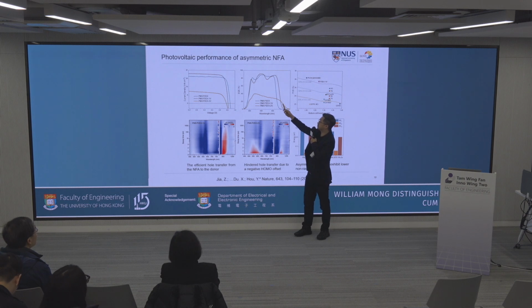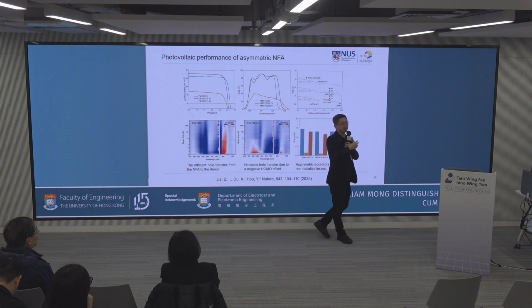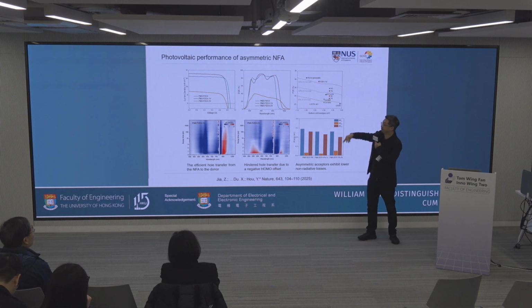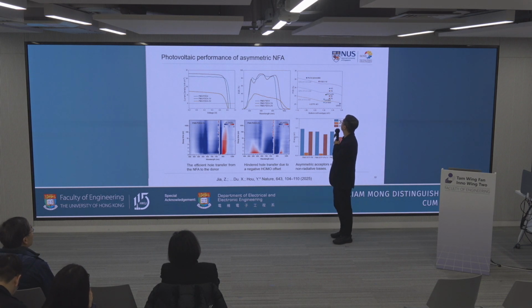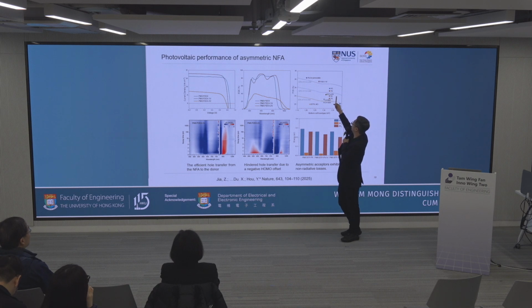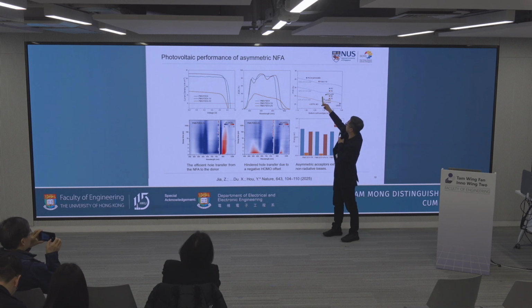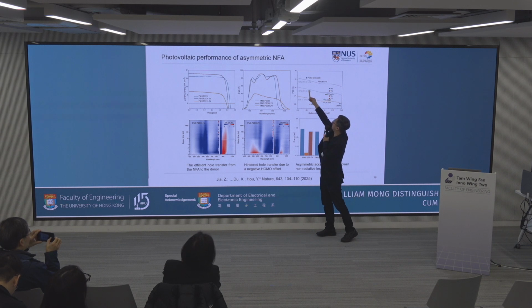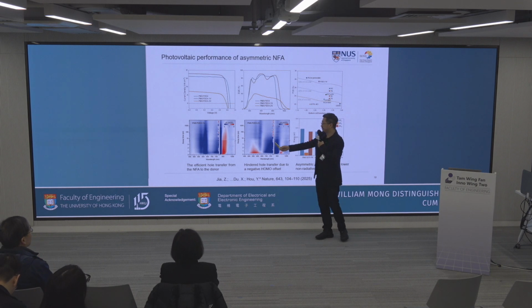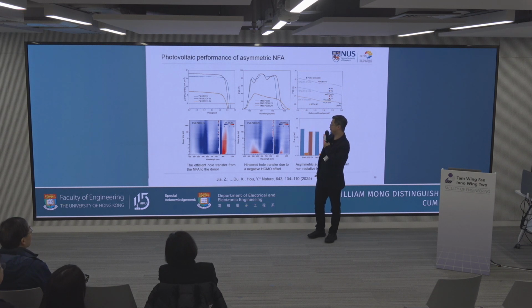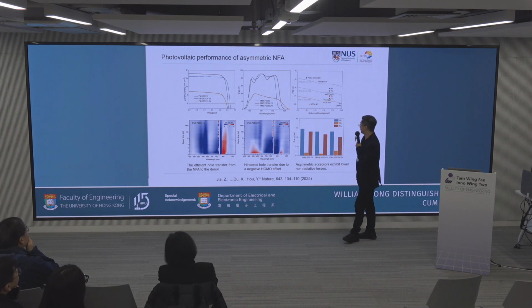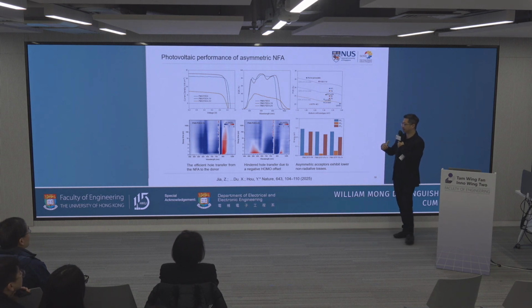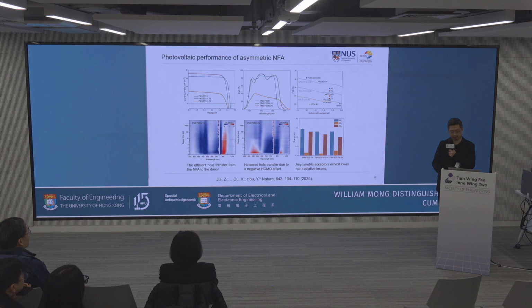You can see the EQE response is quite clear, where it becomes narrower. But it's difficult to become even narrower. And with this one, the EQE actually drops immediately, because as I said, there's no driving force to extract the holes. So this whole EQE just collapses. You cannot get an efficient device. And in the end, this is the band gap. We can tune the band gap from 1.35 to something around 1.27, getting close to this perovskite. And this TA result also shows we need some driving force to separate the holes. Otherwise, we don't see the hole transfer from the acceptor to the donor.